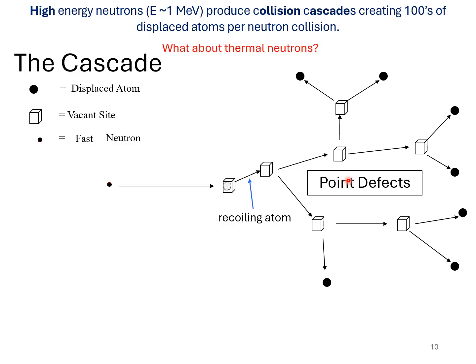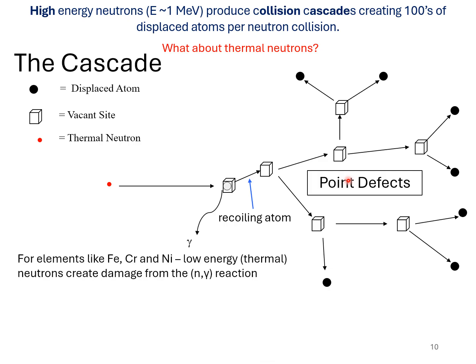So that's high energy neutrons. But what about thermal neutrons? Are they important? Well, they are a little bit. If you have a thermal neutron, it can interact with the lattice by being absorbed by the atom. Thermal neutrons have energies a fraction of an eV. That's not enough to displace the atom, but the gamma photon that's emitted from the activation of an atom by a thermal neutron has a certain relativistic mass, and the recoil produced can cause displacements, typically about 4 or 5.